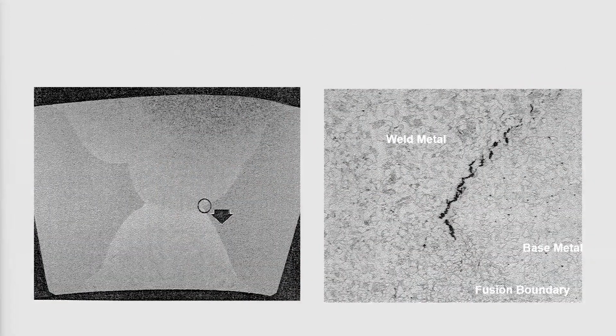A couple of things to note here. You can see that this is creep-related damage that has developed immediately adjacent to the fusion boundary in the weld metal. You'll also notice that there's no heat affected zone here. So this weld has been normalized and tempered. And the vulnerability here is related to two things. First of all, the preferential accumulation of inclusions related to the welding process that was used, which make this area more vulnerable. And the second and very important factor here is the significant difference, or mismatch, in creep strength between the weld metal and the base metal. And it's this creep strength mismatch along with the geometry at this point that has resulted in the damage actually initiating subsurface down in what's called the cusp region of the weld.